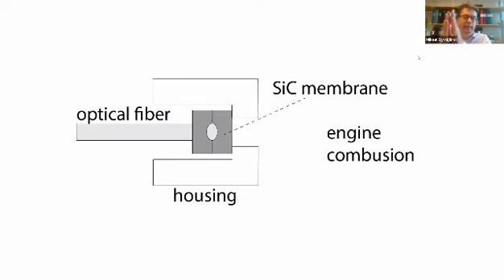And then this silicon carbide should be single crystal because it's transparent, but this other silicon carbide should be polycrystalline ceramic because it's facing the engine, and then you have a lot of heat, and it's actually light from the heat which is disturbing the signal. So then we have a polycrystalline ceramic silicon carbide, which should bond to single crystal. And this we came into, and now we are using this surface reconstruction of silicon carbide to make high temperature direct bonding. This wafer bonding has been explored before, where you have different metals in between, and then you bond them. But in this case, we want to explore the high temperature direct bonding. And that led us to another application avenue than the power devices originally.